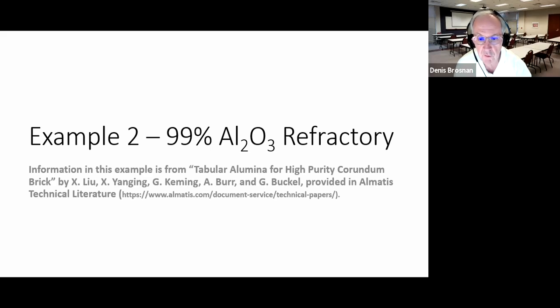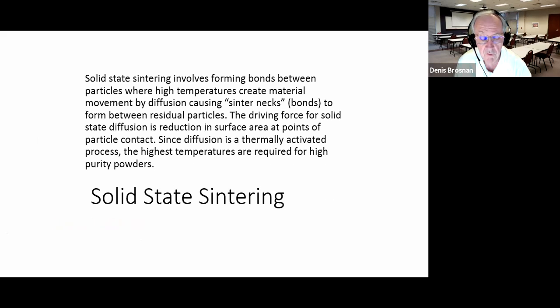So here's example number 2 of a 99% alumina refractory product. This example is taken from a technical paper on the Almatis website. I want to give the authors full credit for everything that's been given here. And so let's go through what they've done. Now, when we're up at 99% alumina, we're not going to have a liquid phase that plays a substantial part in bonding. Okay, we may have some fluxes distributed within the matrix among the aggregate particles, but with 99% alumina, what we're going to do is cause direct sintering, solid state sintering between the particles.